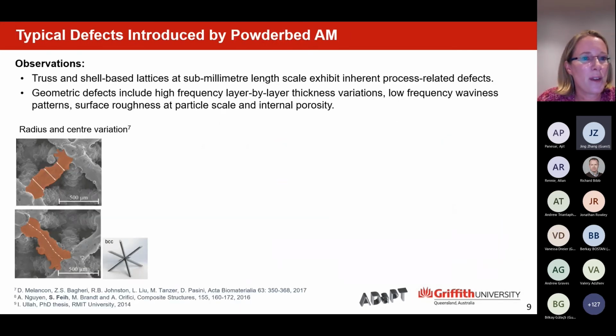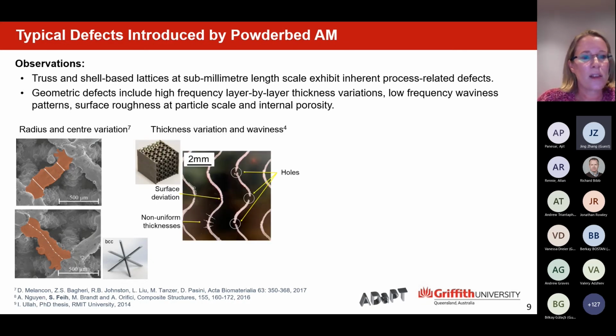Some typical defects, just quickly want to go through this. Not all of this looked at by our group, but so we have for trusses, if we print, you can see here very small printing diameters, again coming down to about 150 micrometer. We have a lot of radius and center variations, meaning nothing is really straight because of the layer by layer printing process. If we look at shells, thickness variations and waviness, again, we see deviations, we see diameter or thickness variations, and we even see holes in the structure depending on the printing and overhanging angles.